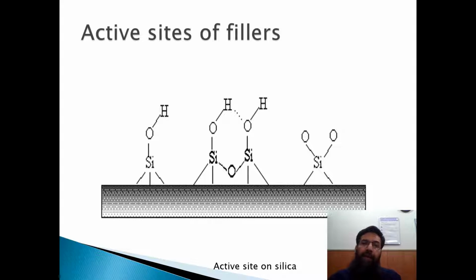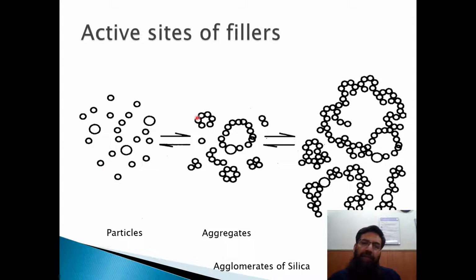Similarly, in the silica, we also have some active sites which are present on the surface of the silica. We do have the hydroxyl group on the surface of the silica, and we do have some silanol group present on the surface of the silica. And in fact, the presence of the hydroxyl group is very tricky, because hydroxyl groups can make the hydrogen bonding, they can interact with each other, and due to this hydrogen bonding we have more interaction of one particle with another particle, and that converts different particles into the aggregates and agglomerates, just like you can see here. The silica particles convert into the aggregates and agglomerates, and that is due to the presence of those active sites on the surface of silica.